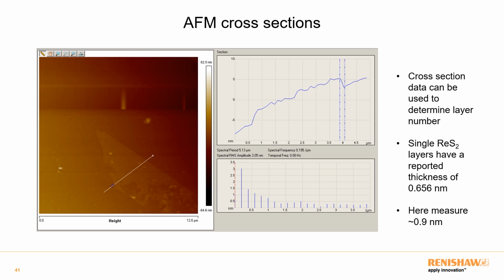I talked about measuring the thickness of the flakes and working out their layer number, and a really nice way to do that is to use the AFM images. Here I've taken the AFM image and measured the cross section running across this line, shown here. I can just look at the change in height between that and the substrate. Single rhenium disulfide layers have been measured in the literature. They have a reported thickness of 0.66 nanometers. Here I'm measuring approximately 0.9, so a little bit bigger, but not so bad.